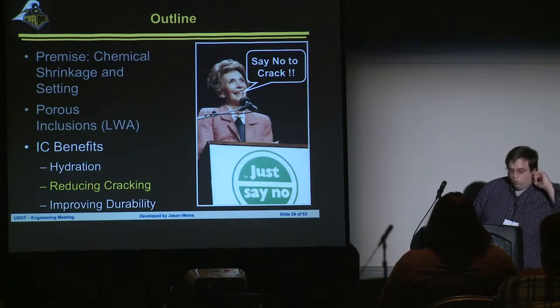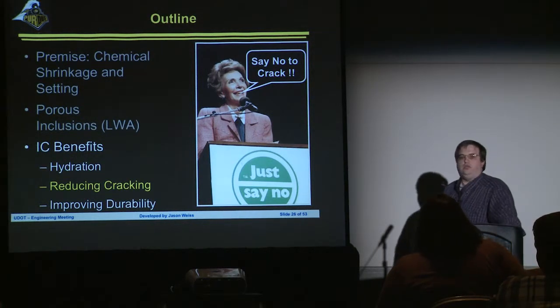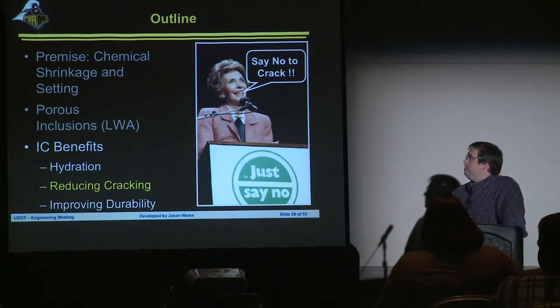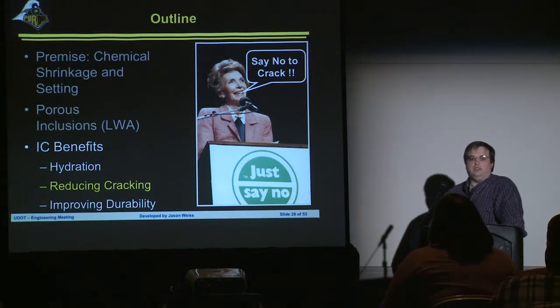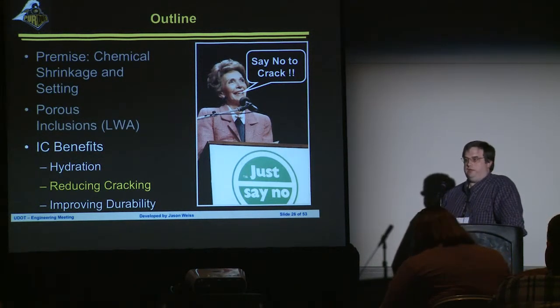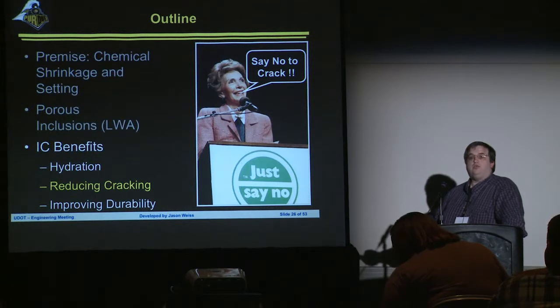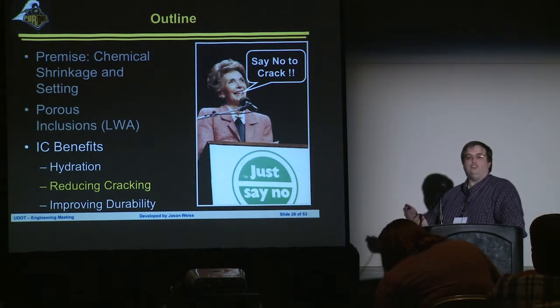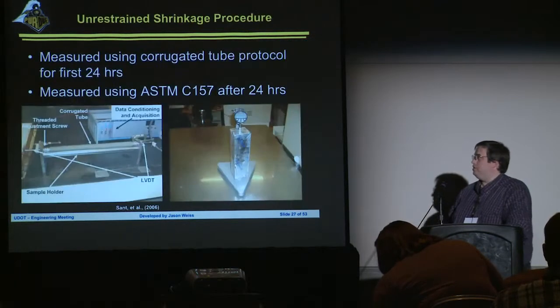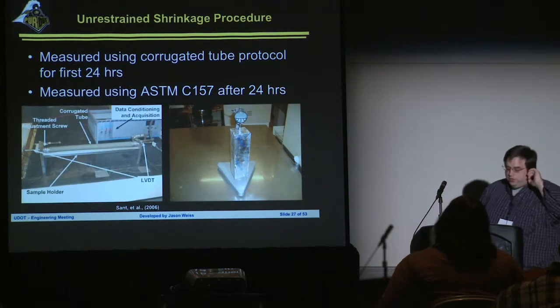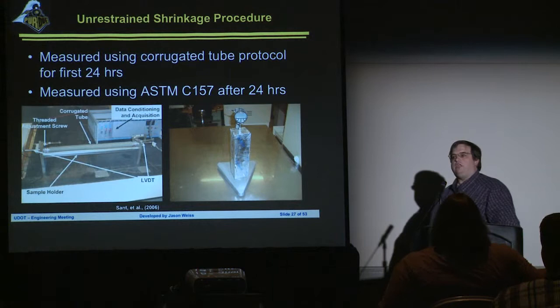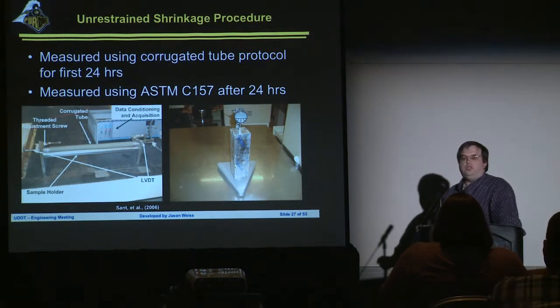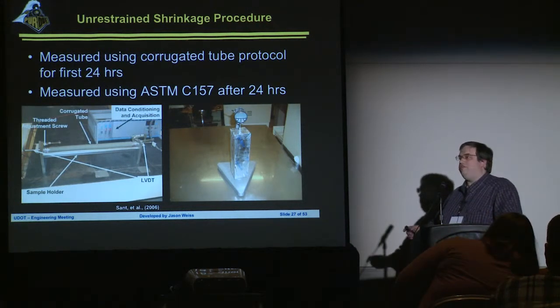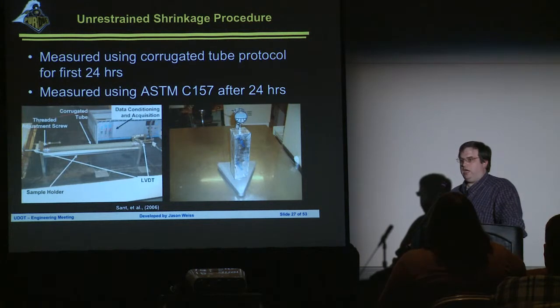Right? One of the most important things that internal curing does, right, is something that Nancy Reagan advocated years and years ago. Say no to crack. All right? Cracks are a problem in bridge decks because they allow water, chloride ions, direct access to our reinforcing steel. Right? So a few years ago, it became really obvious that our conventional measures for measuring shrinkage really start to fail when we talk about high-performance concretes.